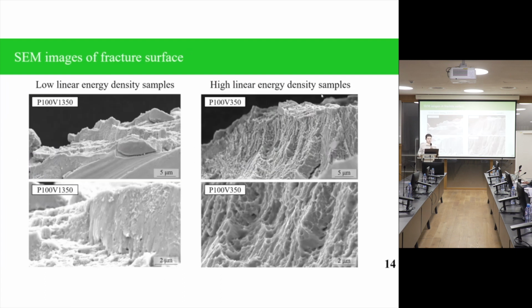And after the first test, after the fracture of samples, the results show that we can subdivide all samples into two groups. The first group involved the samples that were manufactured with low linear energy density input, and this resulted in the generation of defects because of lack of fusion. So in this case, we had crack generation and propagation from void to void, and the overall mechanism of fracture was brittle. While enough energy density input resulted in the ductile mechanism of fracture, when the fracture surface was represented by the cup and cone structure.